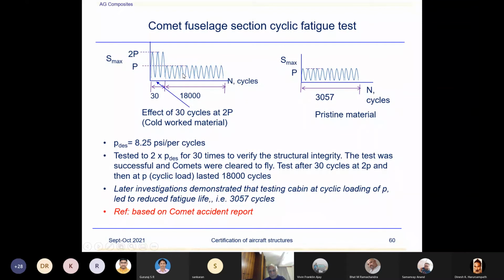However, look at the right. When they tested the cabin with the operating pressure of 8.25 psi, they got only 3,057 cycles. What is the difference? Why is this there? Anyone from the audience? The cause. Why in one case? Defects. Pardon? Defects. No. High cycle fatigue and low cycle fatigue. Yes, that is the reason.